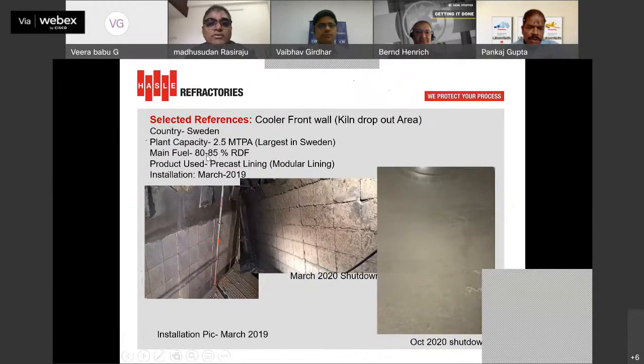This is a plant using 80 to 85% RDF in Sweden, and they are facing a problem in their cooler front wall, just below the kiln. After 18 months, you can see the picture of the modular lining.